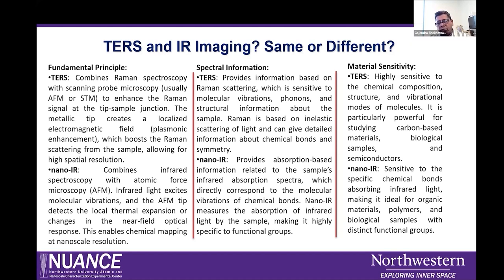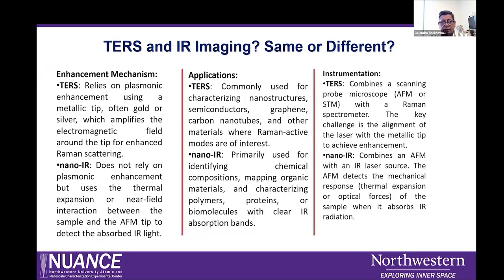Okay, because of the size of the probe, the resolution goes down to 5 to 10 nanometers in this case, as compared to a few microns in the case of FTIR techniques. Okay, so Raman is mostly focused on determining the symmetry of the molecules, or symmetric molecules can be easily identified in the Raman. In the case of NanoIR, mostly it's chemical bond information, non-symmetric molecules, polar molecules. So you can do these things in that.